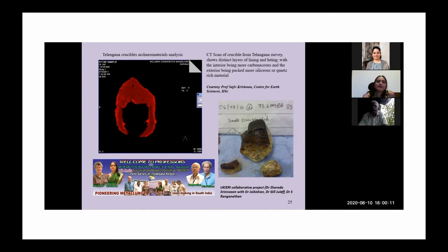And typically these crucibles are made with two layers. There is the inner layer, which is very carbon rich and carbonaceous. And then the outer layer is packed with a lot of quartz and refractory materials and so on. So you can see that, for example, in this CT scan image, the separation of the two layers, there is a lining and the luting and so on. And the outer layer is very siliceous.